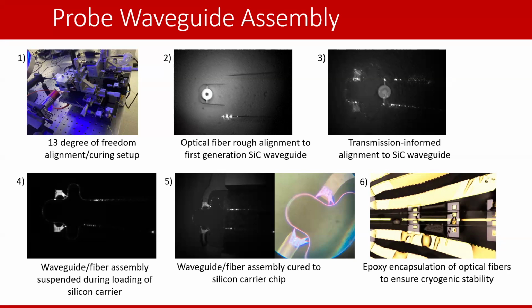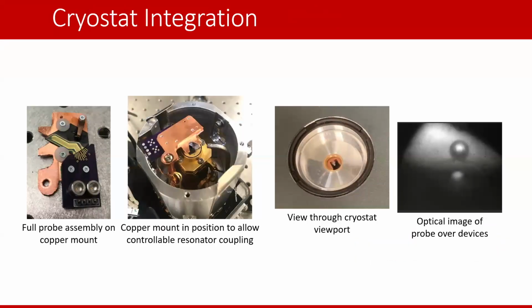We put some UV cure epoxy on it to hold everything in place. The whole assembly goes in the cryostat nicely. This is a S50 Montana cryostat, so it's quite small. This is not that large. I would say, let's see, the chip's about this big, so maybe about that big. And then through simple optical access from the top, you can see the waveguide with respect to these whispering gallery mode cavities. And by moving the piezo stack that holds the chip under test, you can controllably optically couple to these designs.